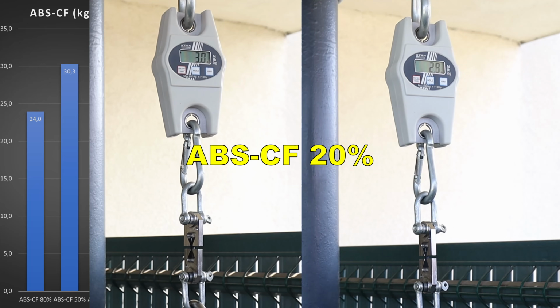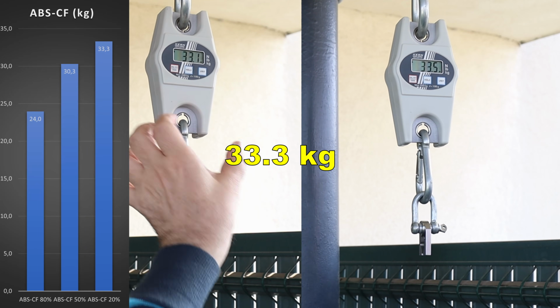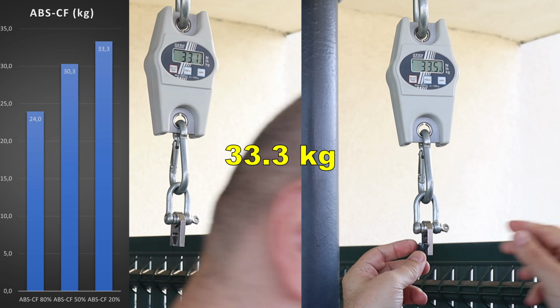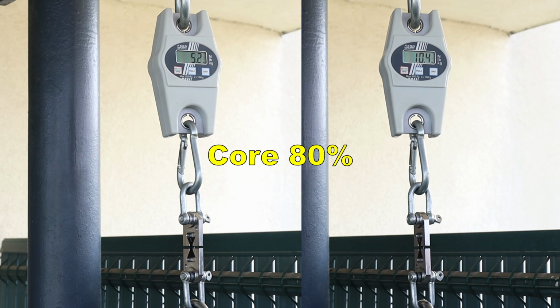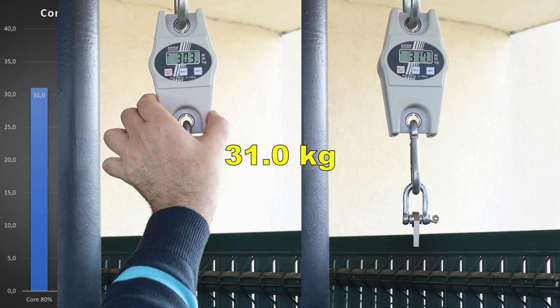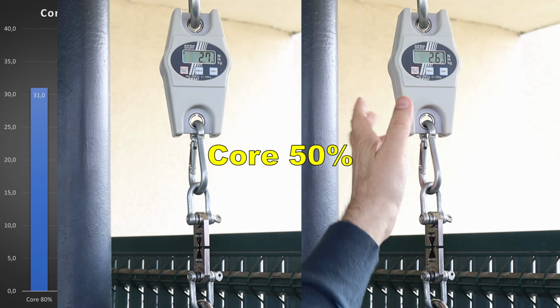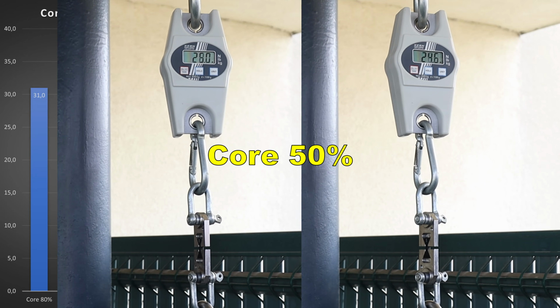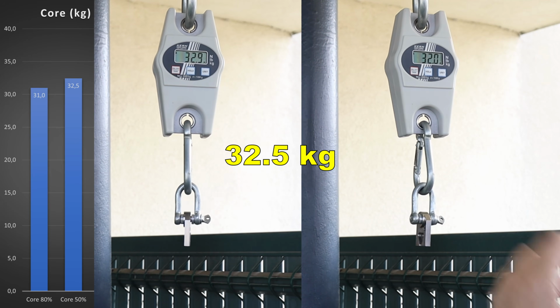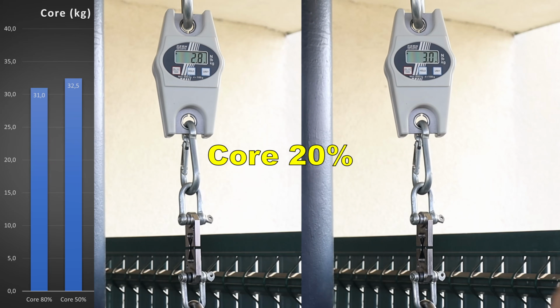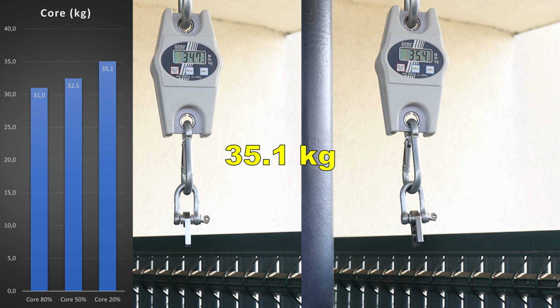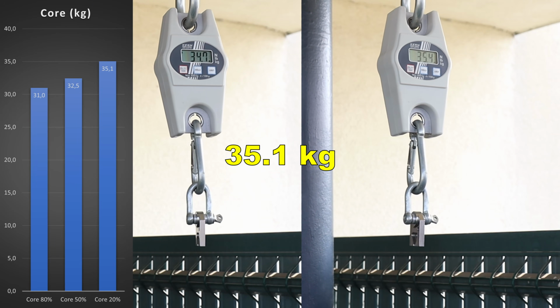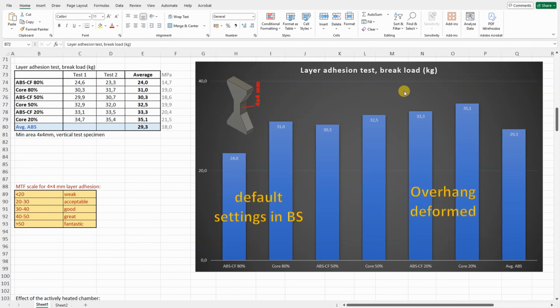And this is with the 20% max part cooling. And now the core version, 80% part cooling, 50%, and 20%, which had some problems with the overhangs, but still stronger. In every case, the core was slightly stronger compared to the regular ABS-CF, and we can see increasing in the layer adhesion with reducing the part cooling.